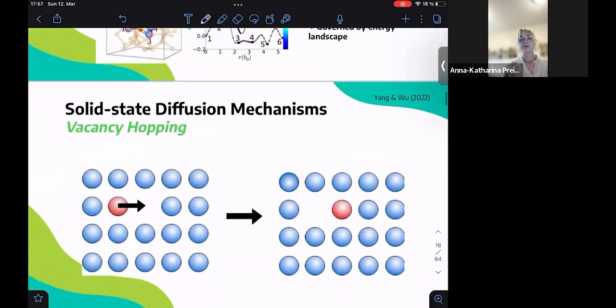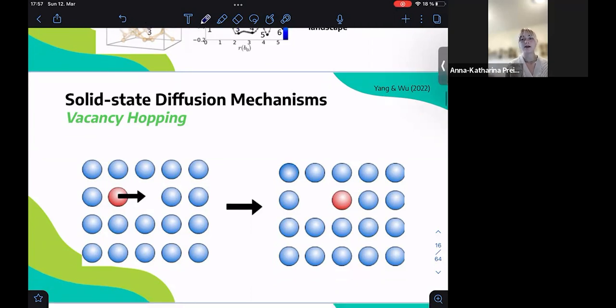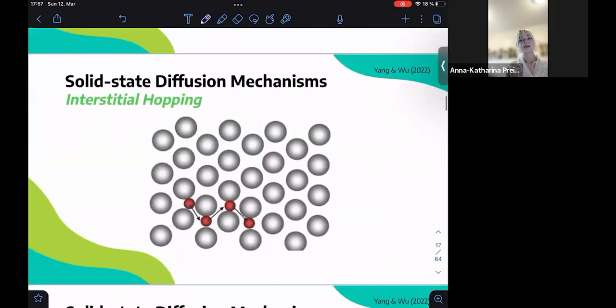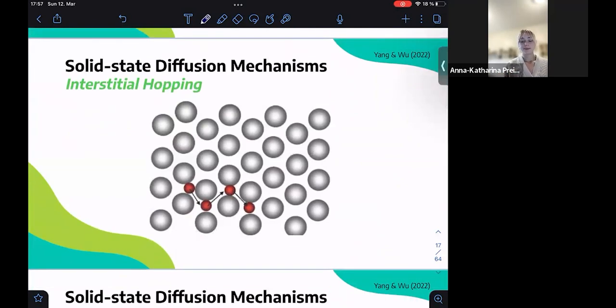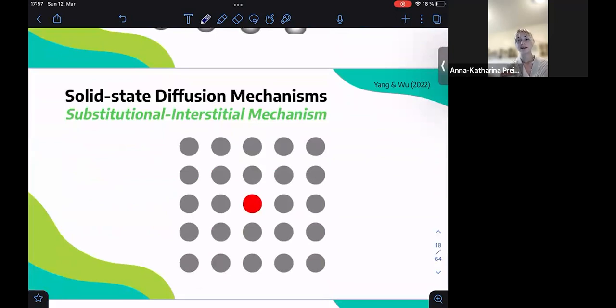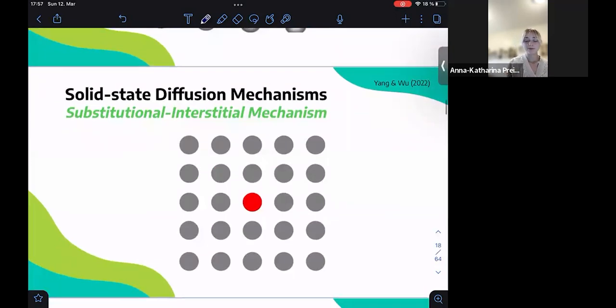In literature, you'll also often see it referred to as hopping. That just means the movement of ions from one site to another. The first one would be vacancy hopping, where if there's a free space, the ion can just move right into it, and that will leave another free space for another ion to move into. Then we have interstitial hopping, which is similar, but it occurs between the atoms of the crystal lattice. And then lastly, we have the substitutional and interstitial mechanism, where, for example, some ion passing through an interstitial site will move into or replace an atom in the lattice and kick this one out. So it's like a combination of these different mechanisms.